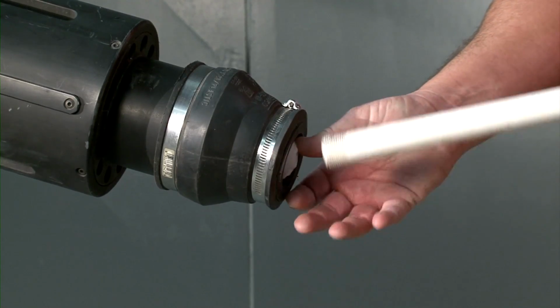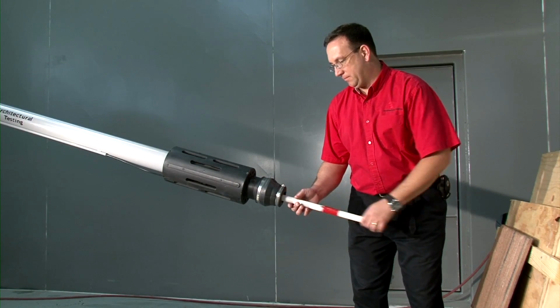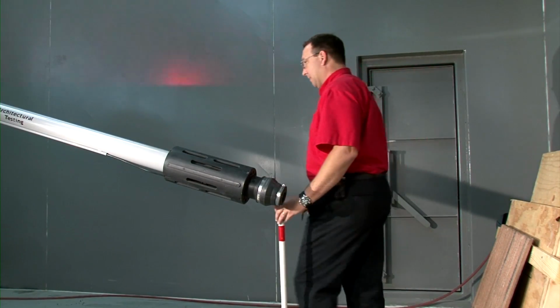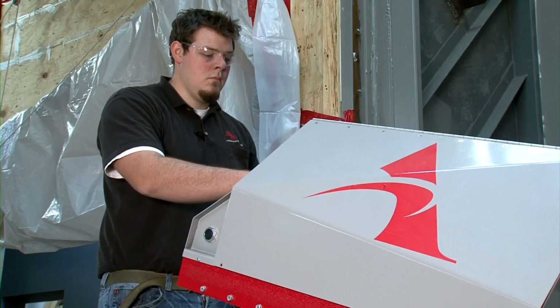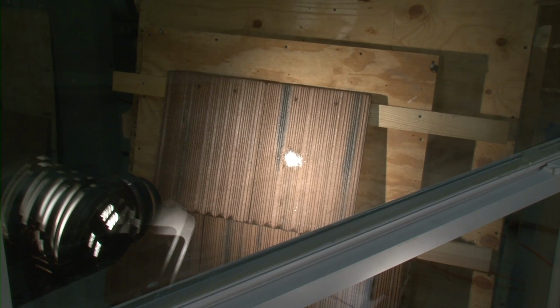In the Class 4 hail test, the 2-inch ice balls are being shot at 104 feet per second, which is the speed necessary to develop the intended kinetic energy. The Class 4 hail test is the most rigorous test using the largest ice balls. Impact locations included edges, corners, unsupported areas, overlaps, and joints. After impact testing, the 3 roofing materials were visually scrutinized and, to pass, the test specimens could not show any evidence of visible cracking or breakage.